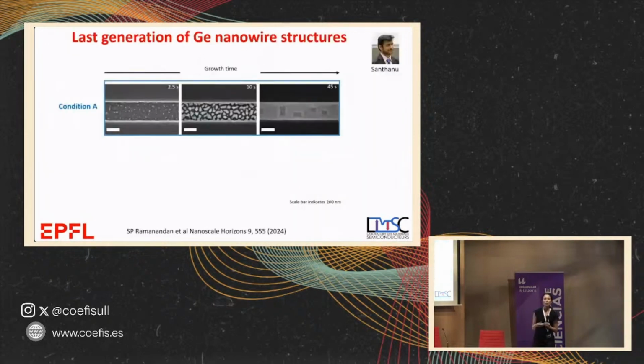Now, just to get a bit into the mind of material science, how we are able to understand what the atoms do, I show you a very small experiment. This is the selective area, this is where they grow, and this is the mask, the anti-sticking mask, and we look at what happens little by little. So typically we would think that the atoms arrive and they just create terraces and they grow, but we saw that they create islands. This is not very good. You would think that would give low quality. So when they create the islands, they start to merge, and at some point they create a continuous wire.